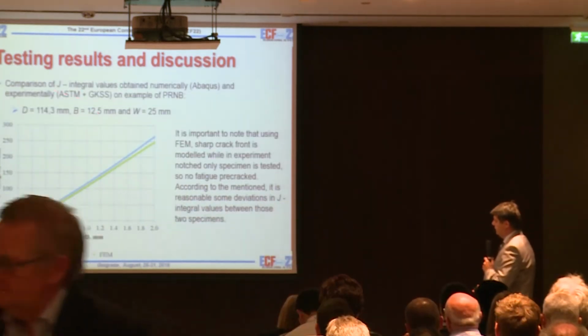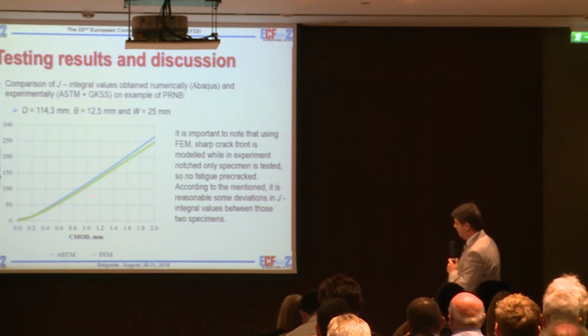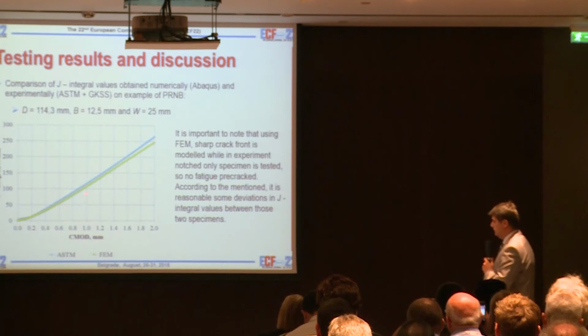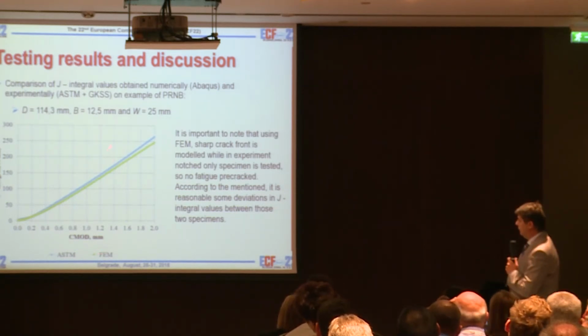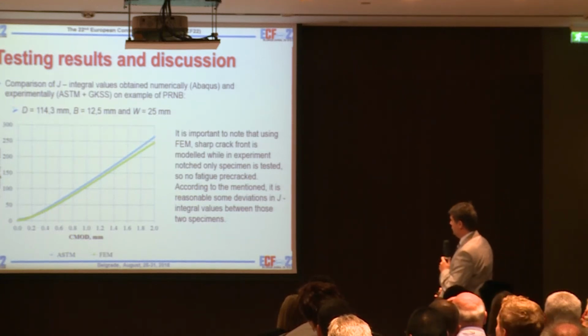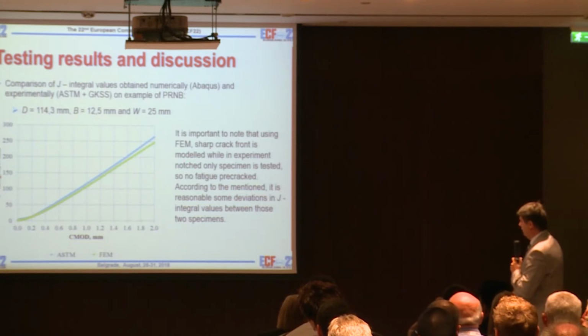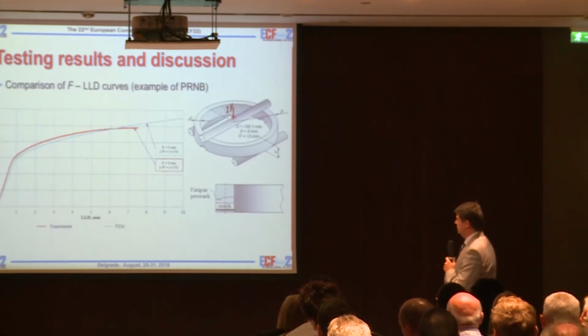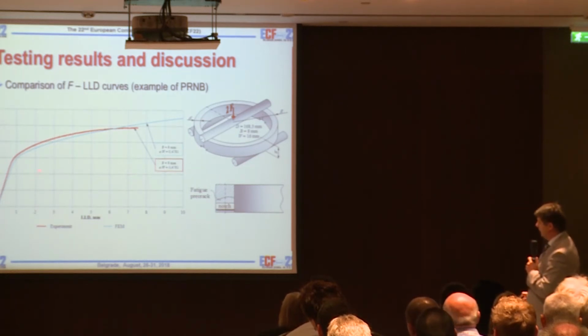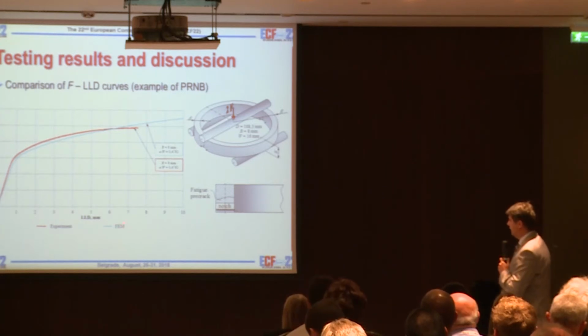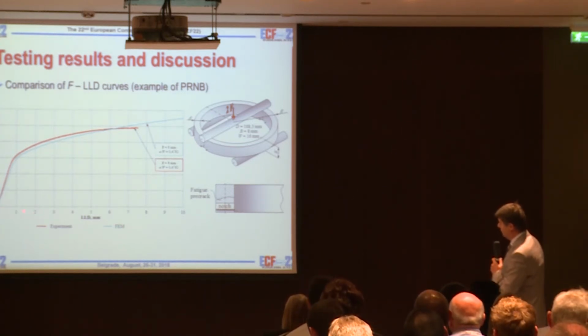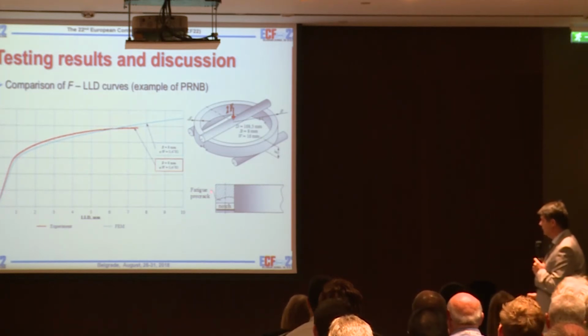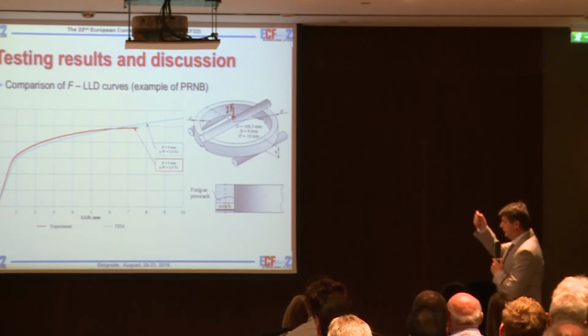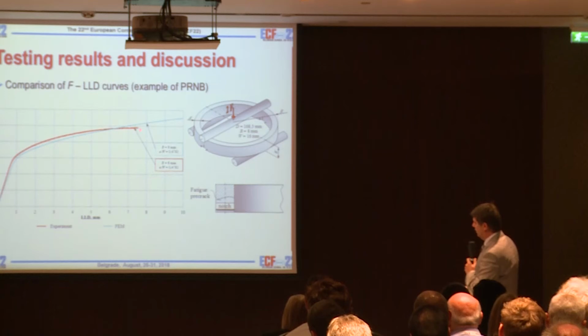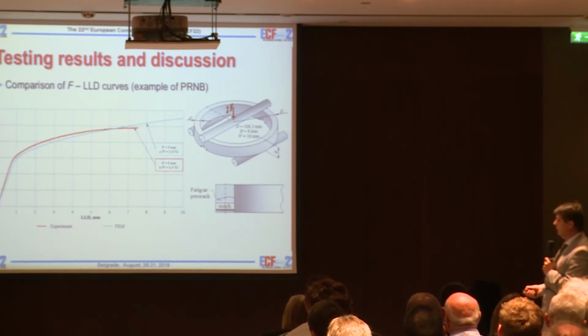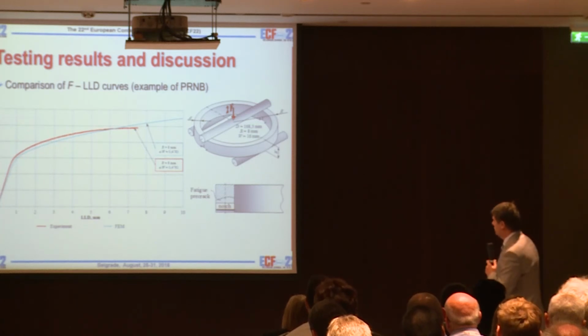So if we compare now the J integral values obtained by the standard and the finite element modeling, we have quite good and similar agreement in these two J values. And this is now the model with only the notched specimen. So we now compare our test and our finite element results. This is the blue line, finite element modeling, and the experiment is the red line. So we consider this real fatigue crack front, and just start the loading up to maximum displacement, and then we take this value of force. So we have quite good correlation between the two values.